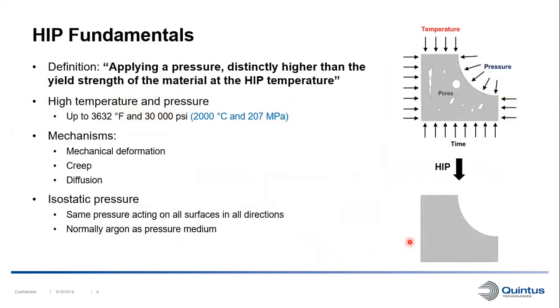So the definition of hipping is to apply a pressure distinctly higher than the yield strength of the material at the hip temperature. So it is a process with high temperature and high pressure. We can go up to 3,600 Fahrenheit and 30,000 PSI in the process. And at this high temperature, the yield strength of the material will be very low. So the stresses that we induce in the component with the pressure will actually be higher than the yield strength. And as we know, when we have higher stresses than the yield strength, the material will plastically deform to, for example, collapse internal pores in castings. So the mechanism that's working during the process is mechanical deformation that I just explained.